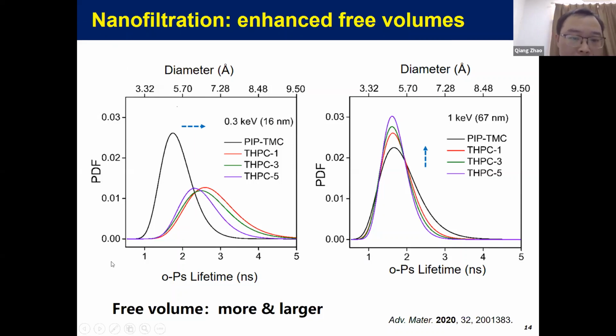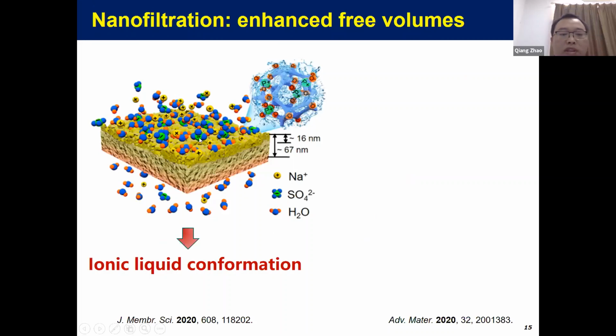In the figure on the left, you can see that at depths of about 16 nanometers down the membrane, the modified membrane, represented by the colored curves, shows more and larger free volume cavities. That means we create larger pores at the very top surface. When you go deeper into the membrane, you will see the free volume percentage increased. If you put these two figures together, you can imagine it like this. At the very top surface, the membrane becomes looser and the pores become larger. In the middle, dense part of the membrane, you will have more pores, although the pore sizes are maintained. Through the combination of this mechanism, the membrane permeability was highly improved.